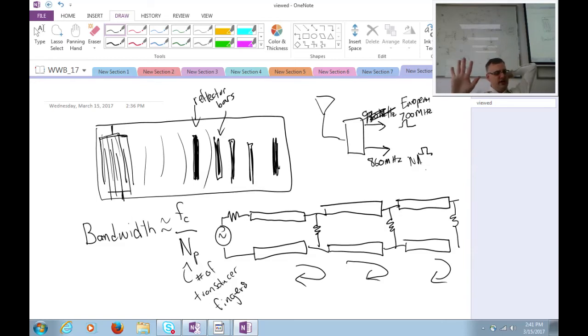Well, on the one hand, these surface acoustic wave devices tend to be a little lossy. Like, you don't get very good transduction. If you get more than a few percentage points of the power into this surface acoustic medium, then you're doing pretty good. On the other hand, you can build filters that are very small, and if you just put an amplifier on them, you can make up for the lost power. So this is how you get a very high Q filter at RF in a tiny, small space inside your phone.